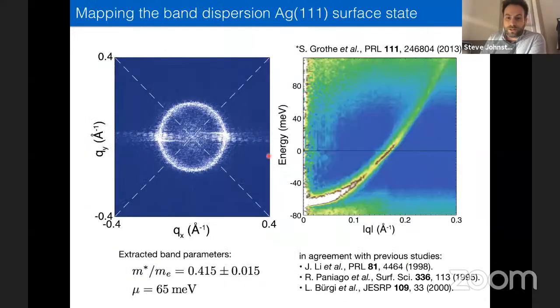You can also do this as a function of bias voltage. So this is an image at the Fermi surface. This is a cut. If I were to just cut along here, this peak here, that's what you're seeing here. Then as you tune the bias voltage up and down, you're basically just tracking the energy contour of the band, right? As I move down in energy, the k-state shrinks as the parabolic band closes. And so you just see a nice 2k_F image of the band structure closing as you move down below the Fermi energy.